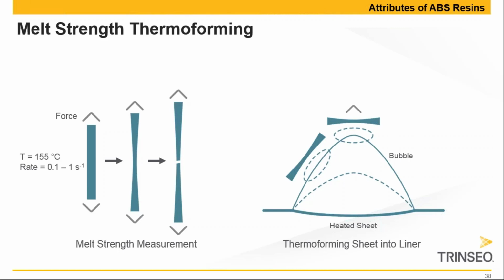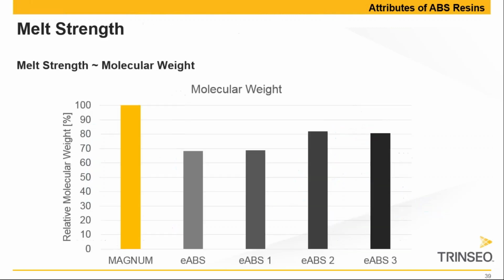Now, the higher the melt strength is, the more resistance you will have against the necking. The less necking you have, the better the wall thickness distribution over the entire thermoformed part will be. Now, melt strength is directly related to molecular weight. And the Magnum shows about 20 to 30% higher molecular weight than the various emulsion ABSs from the Asia Pacific that we have tested.